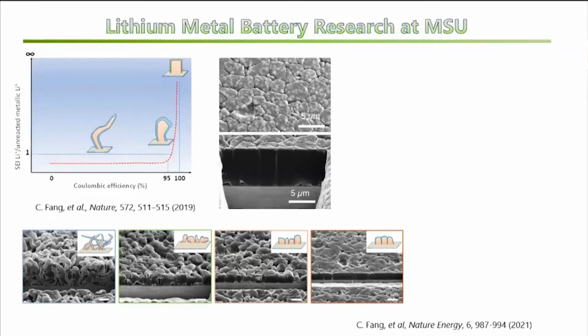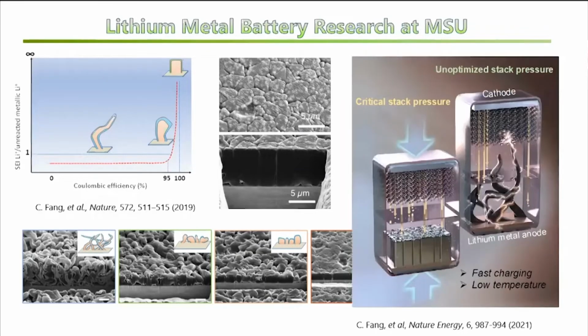So what does this morphology mean in a real battery? I hope this schematic can help you better understand. Without regulation, the lithium metal can easily grow as dendrites to short-circuit the battery, and that can cause explosion. Our approach of using the stack pressure to control the lithium growth during battery operation can significantly densify the lithium and make the cycling very reversible. So this means we can use our high-energy lithium metal battery safely.